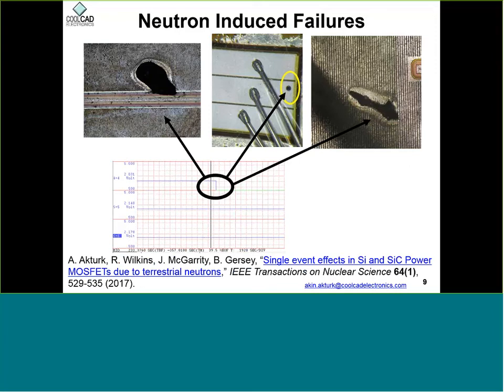And you can see the damage on the die most of the time with your eyes, if the part is delidded or open. You can see a few examples here. As you can see, a hole forms, and it's generally about a millimeter in diameter, so it is clearly visible. And from that point on, the device catastrophically fails. When this forms, the device catastrophically fails and becomes useless.